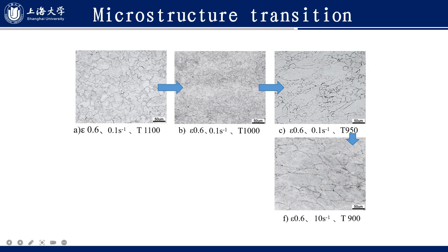We can see the fully dynamic recrystallized austenite at 1100 degrees C, and partial dynamic recrystallization austenite grain for temperature 950, and non-recrystallization microstructure at 900 degrees C.